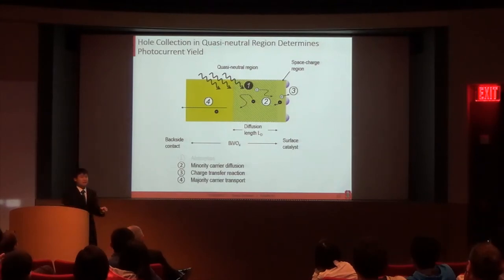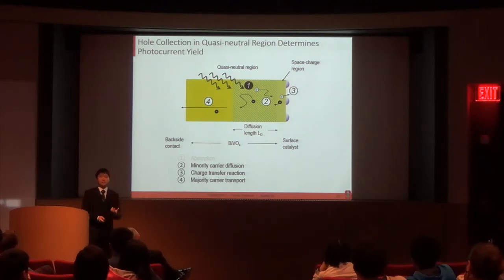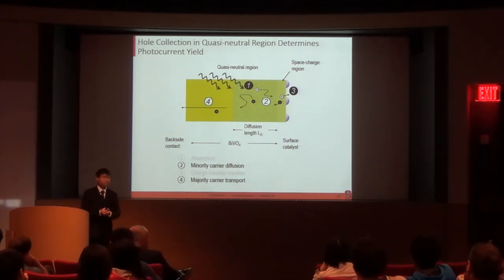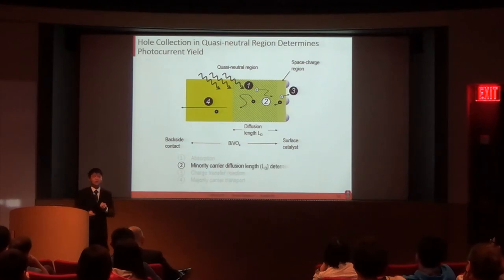So first, we make sure that the film thickness is longer than the characteristic absorption length, so the absorption is not limiting. And then we compare the photocurrent for water oxidation with the photocurrent for sulfite oxidation in hole scavenger solution, and make sure that the surface catalyst is sufficiently efficient for water oxidation. And finally, we also eliminate the possibility of majority carrier transport by choosing the molybdenum doping level to provide sufficient electronic conduction within the film thickness. So it leaves the only possibility to be the minority carrier diffusion length that could determine the photocurrent.